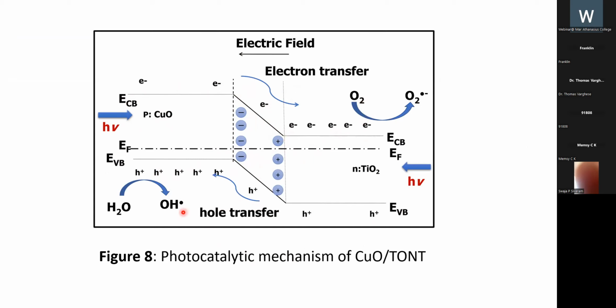The electrons on the N-TiO2 react with O2 adsorbed on the surface to form the superoxide radical, whereas the photo-generated holes left in the valence band react with water molecules to yield the highly oxidative hydroxyl radical, which is a strong oxidizing agent to decompose the dye. This reactive radical combines with organic compounds to form carbon dioxide and water.